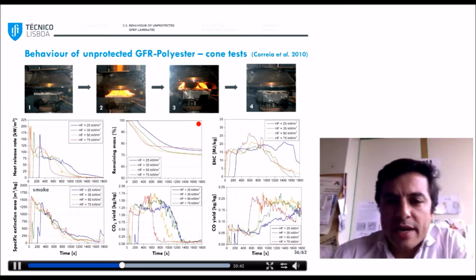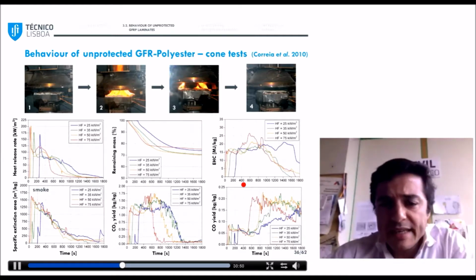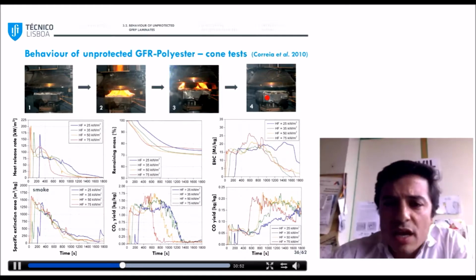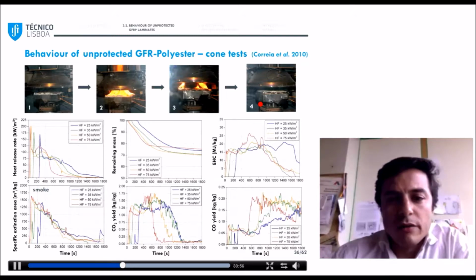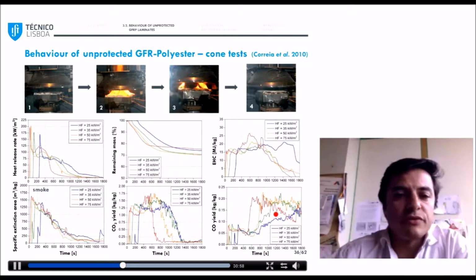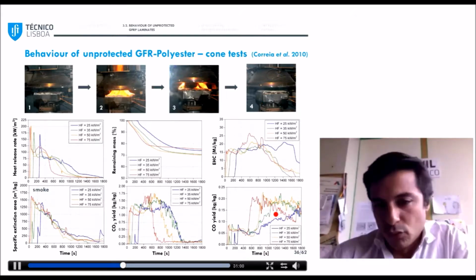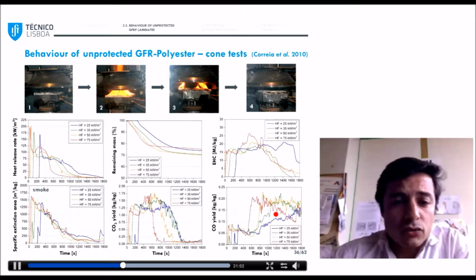In a third stage, when the remaining resin is reduced, the flames start to die down, and the release of heat, smoke, and CO2, they all decrease. Finally, in a fourth and final stage, after all resin is decomposed, you see no further signs of thermal decomposition in terms of heat, smoke, and CO2.